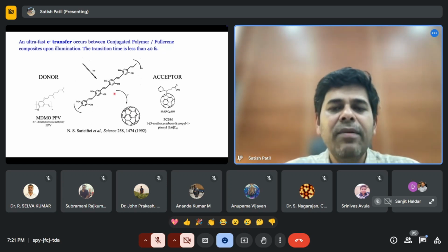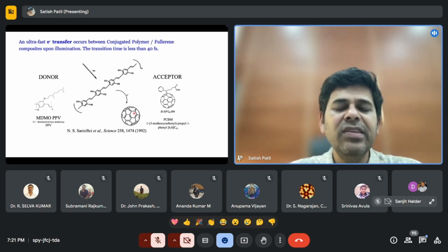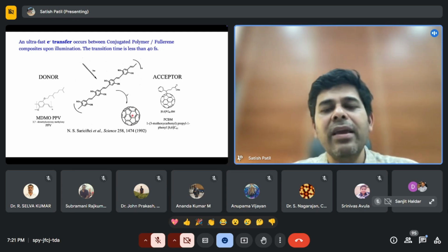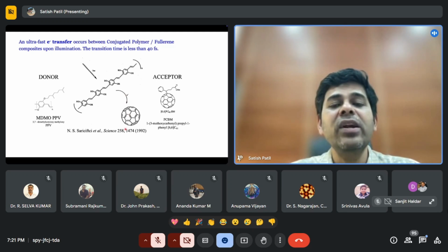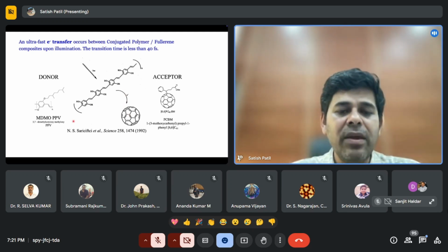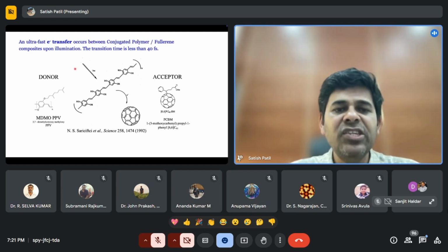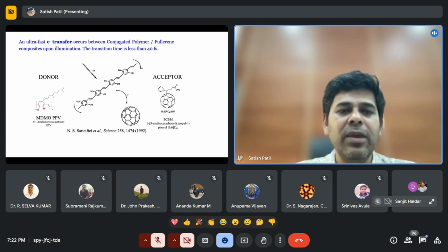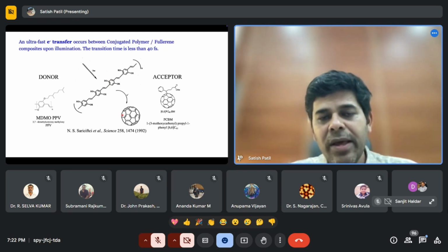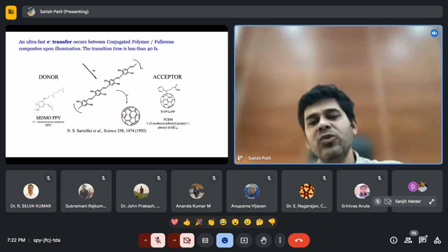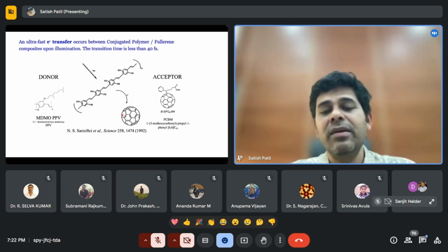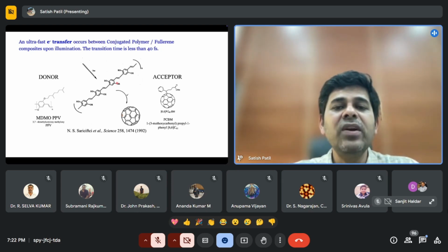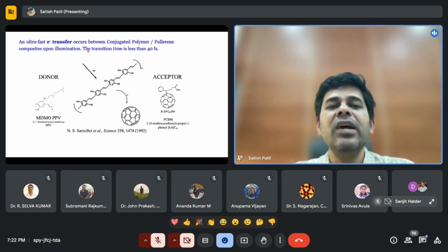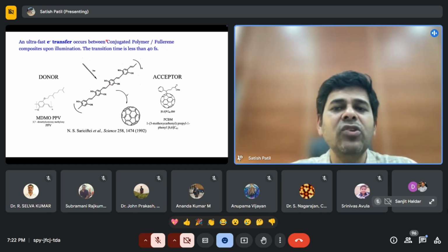It's a seminal paper in the field where people used a polymer and C60. C60, if you are an organic chemist, has a very high electron affinity. It can actually take away a maximum of 6 electrons. So the idea here, the group up in Santa Barbara, they shine the light on a polymer like MDMO-PPV. They use this material, shine the light, they photo-excite, and they transfer the electron. Remember that I was saying that you generate exciton, and it is very hard to dissociate exciton. So this was the major breakthrough in the field. What they observed is you can dissociate excitons and transfer the electron if you use these materials next to each other. And they found a very fast electron transfer between the conjugated polymer and fullerene.